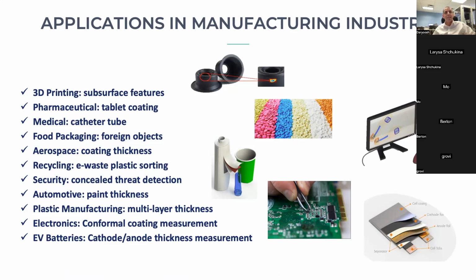In the pharmaceutical space, the tablet coating, particularly there are tablets that are multi-release, so the coating layers are very important to control the thickness of. This is an area the terahertz measurement can be a useful technique to be applied to. In the medical space, for a surgery catheter tube, there are multi-lumen tubes that are separated by thin walls within one tube, and each is responsible to take certain liquid in and out of the patient's body. And that has to be controlled very precisely so those liquids don't leak into each other and make issues with the surgery procedure, for example. So that's one area that terahertz measurement is a good technique to help with the quality check.